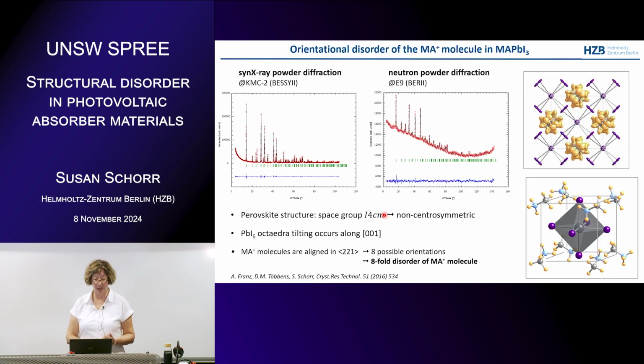So we studied the orientational disorder of the methylammonium molecule in methylammonium lead iodide. We combined synchrotron X-ray powder diffraction, this was done at BESSY, and neutron powder diffraction. The space group we found for the perovskite structure is I4cm, so this is a non-centrosymmetric space group. The octahedra are tilted along the 001 direction, and we found 8 possible orientations of the molecule. So these are the 8 different orientations, or here in the bulk, these 8 different orientations. That means we have an 8-fold disorder of the molecule in MAPI at room temperature.